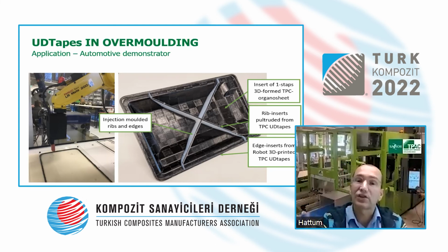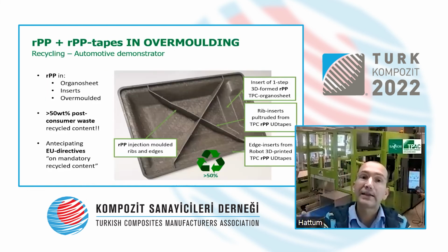The part consists of an overmolded organo sheet shape. The edges as well as the center have local reinforcement 3D printed on a robot set, pultruded sections in the middle. This is the ordinary glass fiber polypropylene variant that is currently the most widely used material in the automotive industry. The same part, basically, we developed in another project we ran with Stellantis.